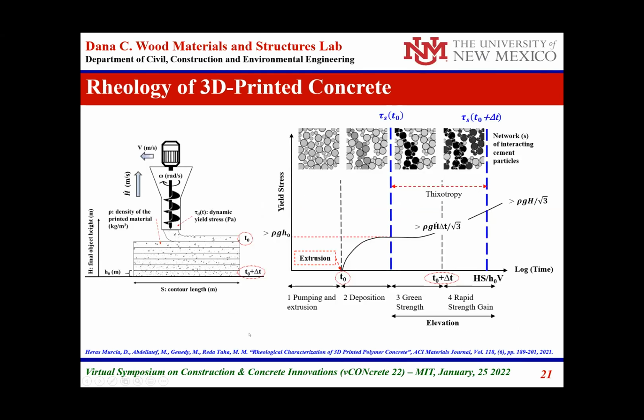The whole discussion here is, of course, based on the material strength, not on stability, which we'll talk about later. As you print the material and do the extrusion at time T sub 0, the material strength or yield stress is growing, and the material changes from the fluctuating, very fine powder, cement powder, to hardened material and the network of interacting cement particles.